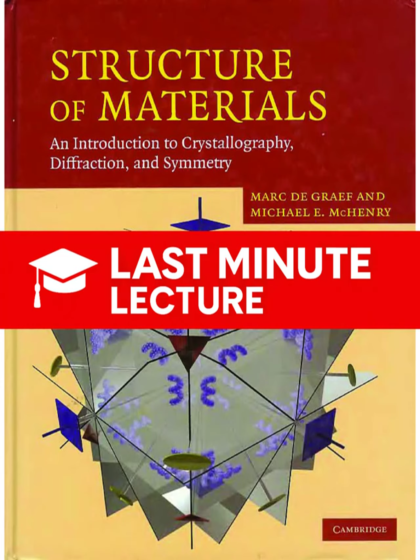Okay, yeah. It's defined very simply. It's just the ratio of the amplitude scattered by the entire atom, all Z electrons, to the amplitude scattered by our reference point, which is a single electron. So if f equals 5, the atom scatters 5 times as strongly as 1 electron. Exactly. Now, if all Z electrons scattered perfectly in phase with each other, then f would simply equal Z, the atomic number.